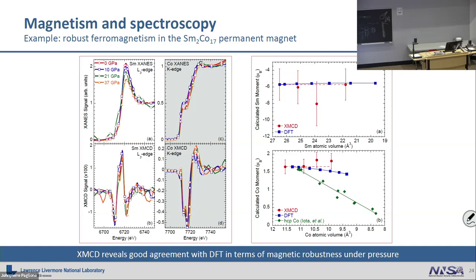This is particularly a samarium-2 cobalt-17 permanent magnet that we looked at many years ago, and the fact that you have this signal in the channel tells you that your samarium ions are magnetic, and that they are ordered in this case. And then you can also do the same thing on cobalt, which is really cool, so you've got the same sample in there, and you can measure both of the different edges. So if you had a sample and you didn't know if your rare earth ion was magnetic or your iron was magnetic, you can distinguish them with this. You could also see if one of them lost its magnetic channel.